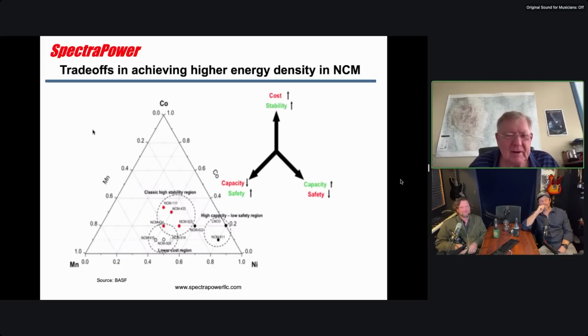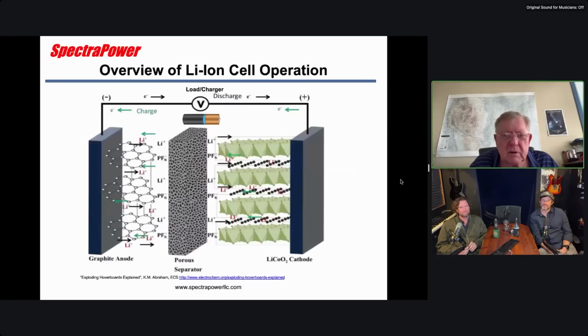Well, the other pro tip I like to give people for lithium ion is if you want to get maximum life out of your cell or your battery, you really shouldn't fully charge it or fully discharge it. And the reason is, let's see if we back up to here. So when you fully charge a cell, you're moving the maximum amount of lithium ions into the graphite that they'll accept. Okay. So what happens in one of the early failure modes in lithium ion is that this graphite in the planes can do what's called exfoliation.